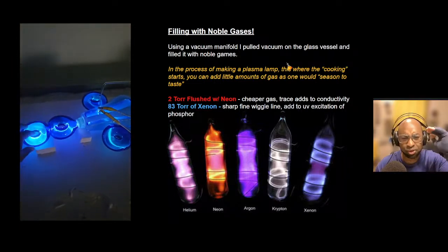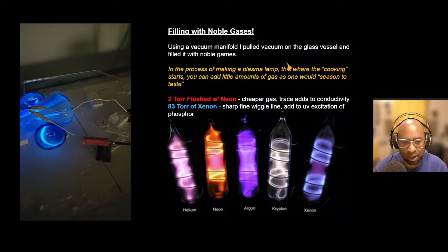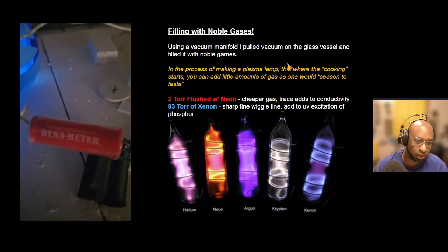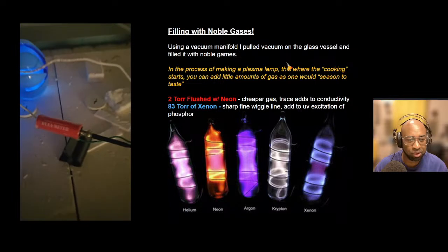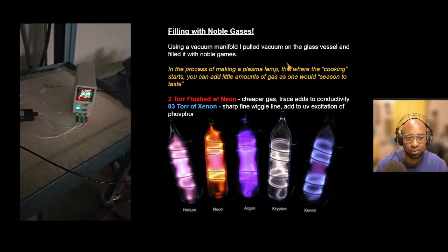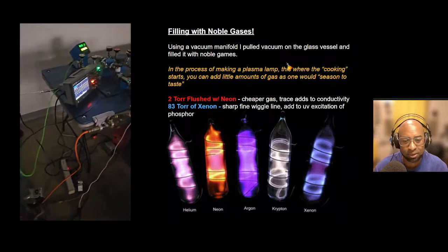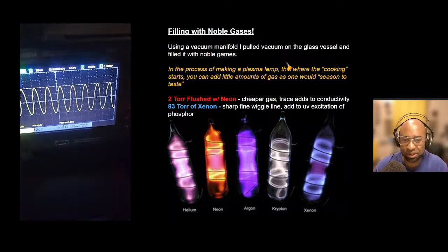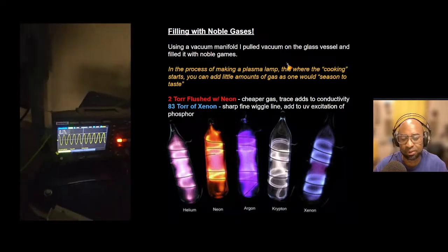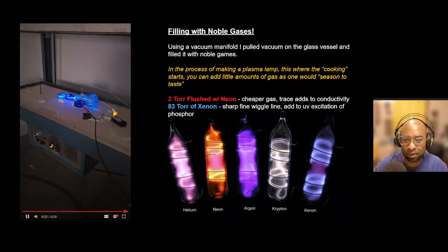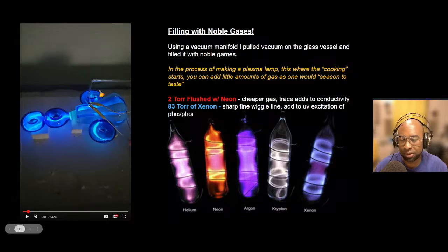And I add up to 83 torr of xenon, which typically produces some kind of sharp, fine wiggle line of light blue that also adds a UV excitation of the phosphor. So you could try this mixture and see if it works for your form. Again, this form is a bit voluminous, but it also has all these different channels that the gas has to travel through and all the plasma has to wiggle through. So I was really dialing things in to the right pressure that allows that to be pretty easy and abundant here.